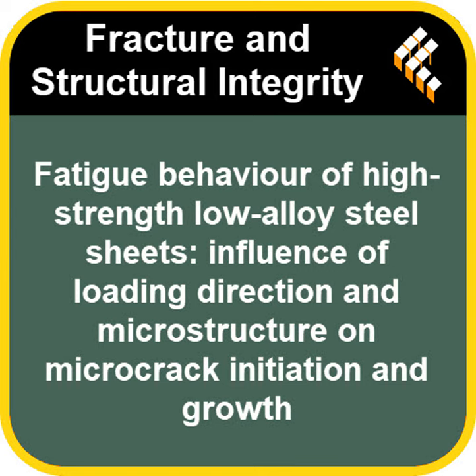So for example, at a low strain level, like 0.1% plastic strain, the DD sample's diagonal actually hardened a little bit initially, maybe 3%, before they started to soften. But the RD and TD samples just softened right from the beginning. Then at a higher strain, 0.3%, the RD and DD samples just softened continuously. But the TD samples, transverse, they did something surprising. They initially hardened by about 4% before they began to soften.